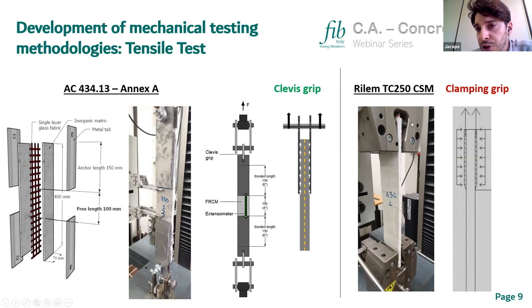provided a different solution with a clamping grip. So in this case, there is pressure at the ends of the specimen, which is put between the clamps of the tensile machine. And so in this case, we do not allow the fabric to slip within the mortar. So we have a complete characterization of the composite. And so usually we have also the failure that is due to fabric breakage more than slippage.